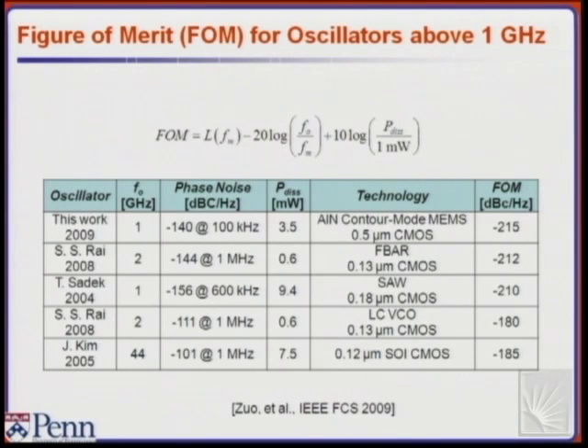I can see 1 to 2. And you can see how we're basically superior to any other, I would say, comparable to any other mechanical device that is commercially available, like a SAW or an FBAR. And definitely better than LC based, and that's just because of the Q levels that you can achieve with these mechanical structures.